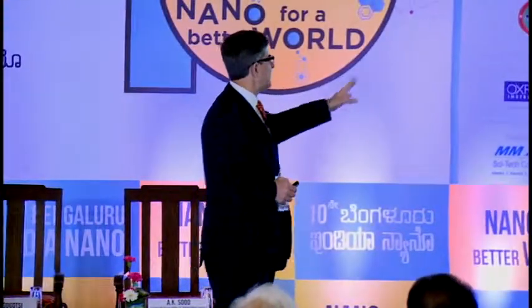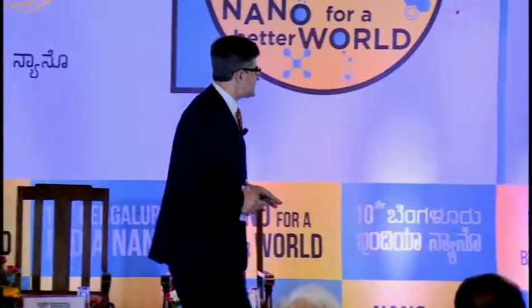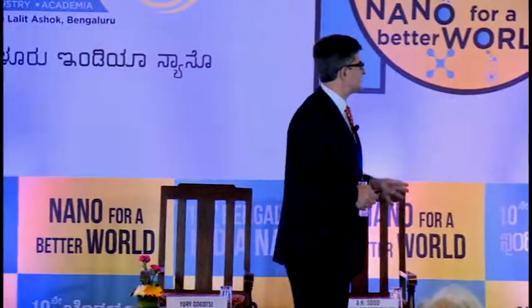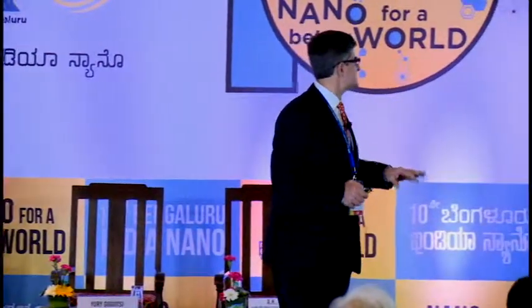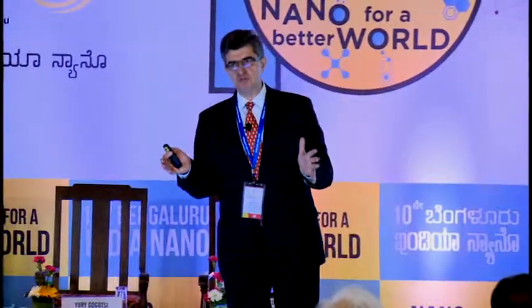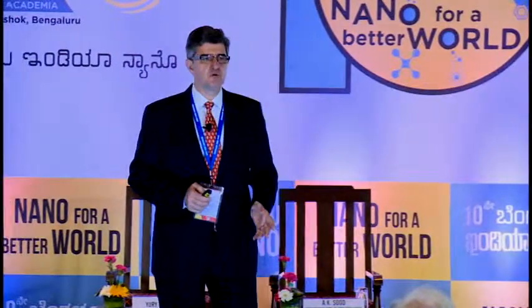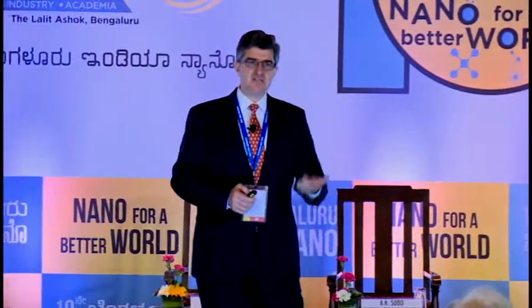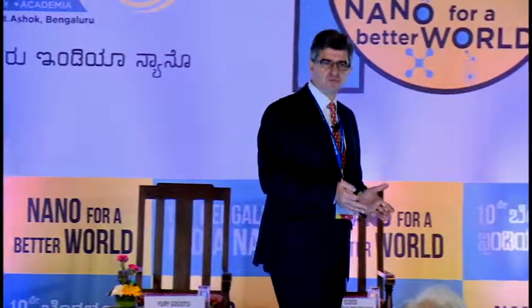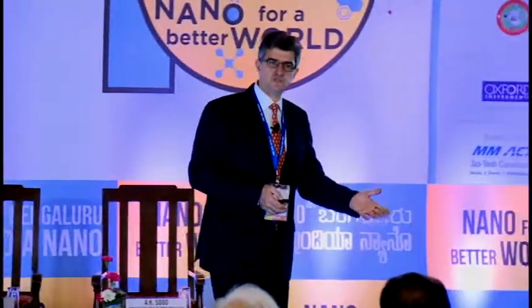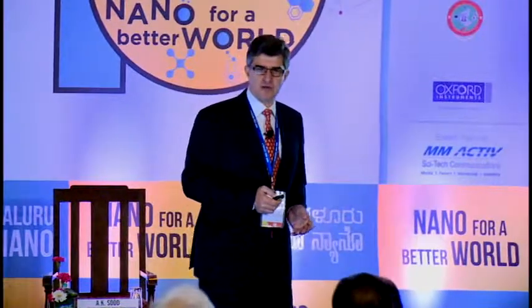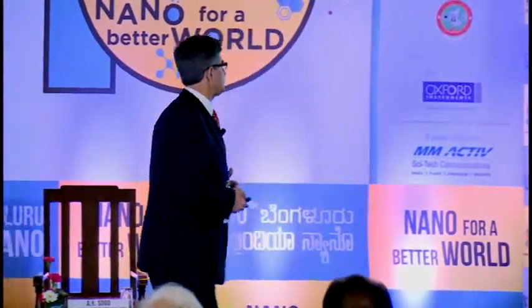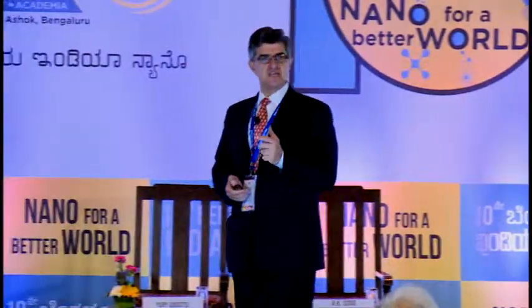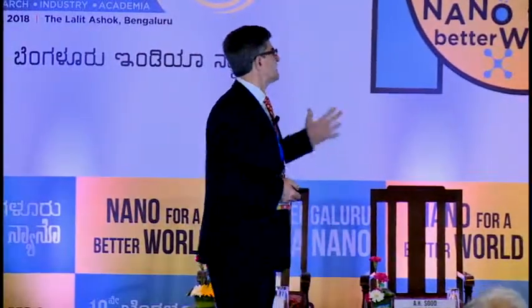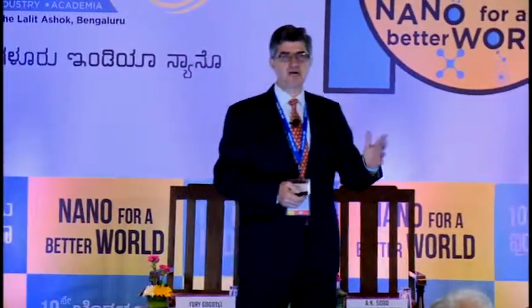But people look into hydrogen storage, thermoelectrics, lasers, femtosecond lasers, nonlinear optical devices, water desalination and purification. For example, MXene, because it has a very high negative charge on the surface, from minus 30 to minus 80 millivolt zeta potential, if it has large ions like uranium, chromium, lead, it can capture them from water, even in the presence of other ions. That was shown even for seawater, when there is plenty of sodium around, flowing it here. Gas separation membranes, sensors, both gas sensors and biosensors. Composite materials, electrocatalysis, HER, OER, ORR.